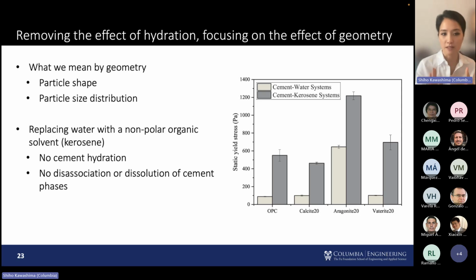Okay, so we eliminate the effects of hydration, and then we measured static yield stress. So here we're reporting the same measurements from before. So the light gray is the cement water systems, the paste. And then the dark gray, those are the cement kerosene systems. And so what we're seeing is, okay, even without the effect of hydration, aragonite is leading to an increase in static yield stress compared to the other polymorphs, calcite and vaterite. So there's definitely a shape effect, size effect.